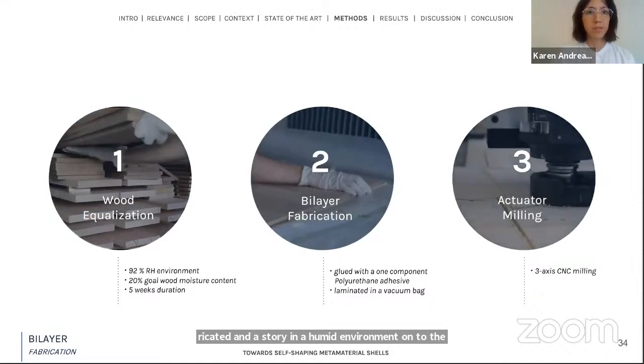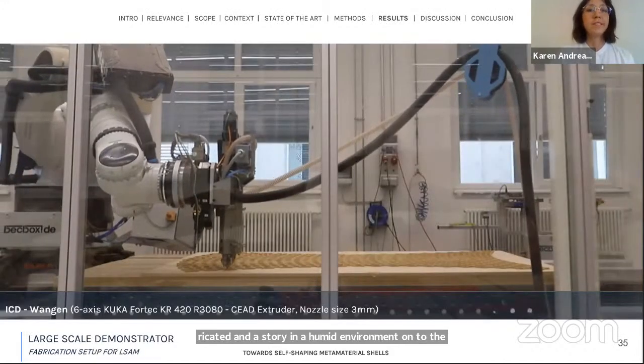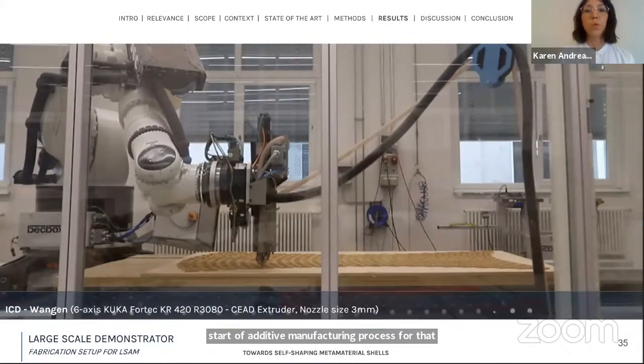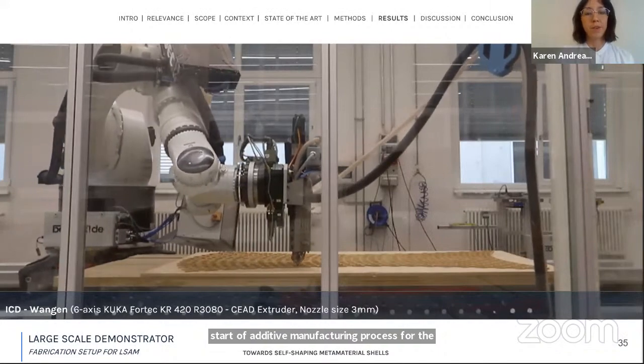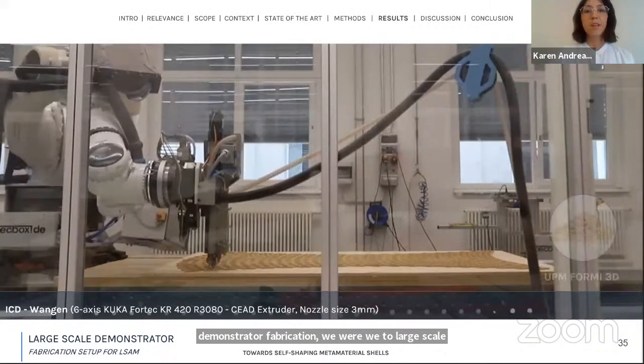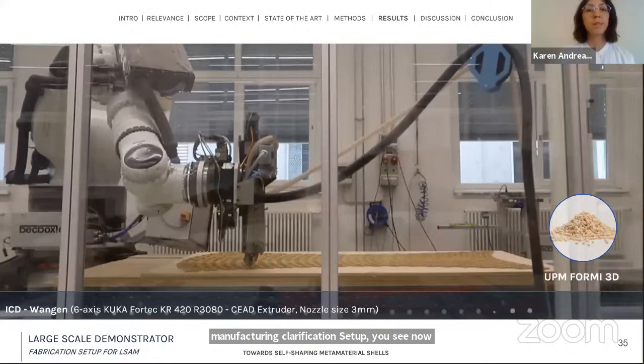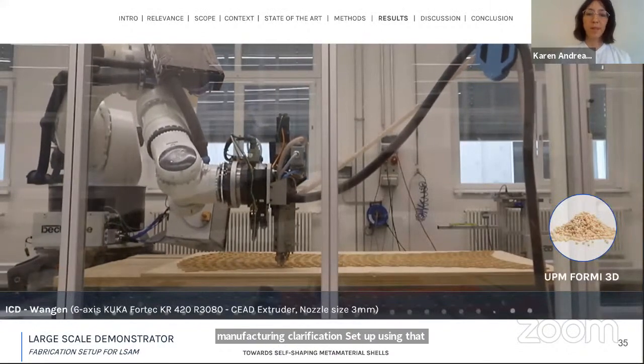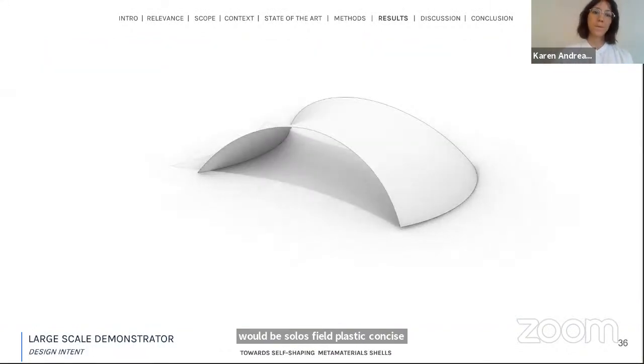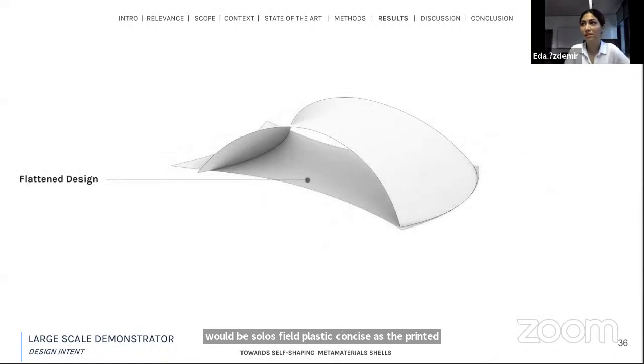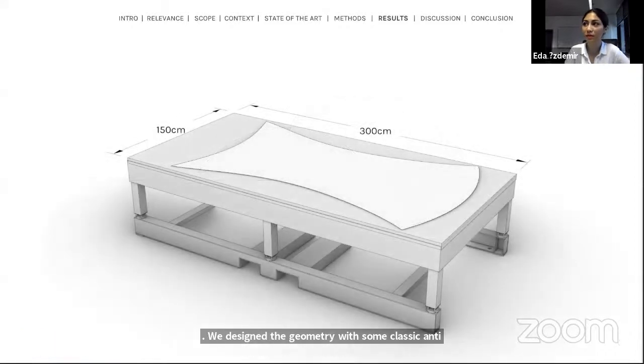additive manufacturing process. For the demonstrator fabrication, we work with a large-scale additive manufacturing fabrication setup using a wood-based cellulose filled plastic composite as the printing material. We designed the geometry with synclastic and anticlastic areas while taking into account the bilayer's radii limitations, material and pattern flexibility, and the fabrication constraints.